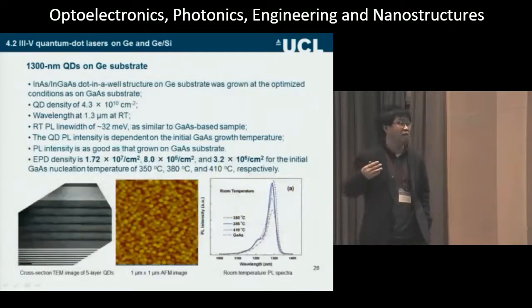We just use the conventional III-V quantum dot growth on germanium. Due to time limitation, I'm not going to go through detail, okay? It's published anyway. You can see we don't have any defects in cross-section TEM. And also, AFM shows quantum dots look beautiful, uniform. And also PL, with optimal growth conditions, you can get almost as strong as on native gallium arsenide substrate.